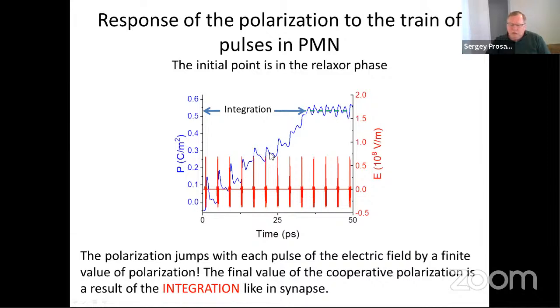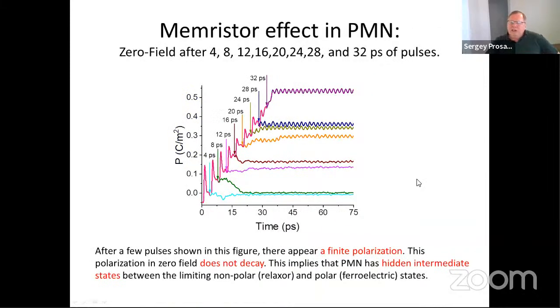It is very interesting to understand: are these intermediate states stable or metastable? For example, we know that this ferroelectric phase at the top is definitely stable. And to answer this question, we did calculations after 4, 8, 12, 16, etc. picoseconds by switching the electric field off, and we see that polarization stays constant, more or less, of course.